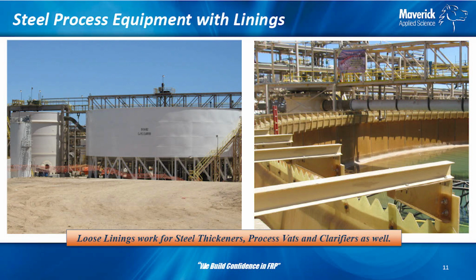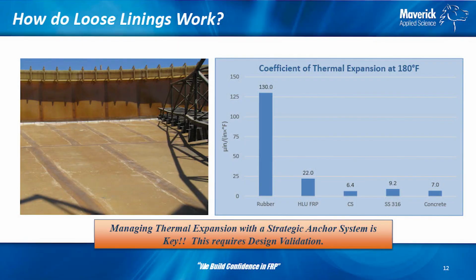In mineral processing, it's going to be a raw, concentrated aggregate where it's going to have rocks and sand and things like that in there as well, mixed with, say, copper sulfate in a copper process. And basically they're letting the solids settle down to the bottom, and that's what that sweeping rake does. And then the pure clear material comes over the top. We have these weir plates here where it trickles into the trough, and then they cut off the sweet material. Should be cleaner, and then it's further refined after that, just to give you a little insight to that. So what makes them work?